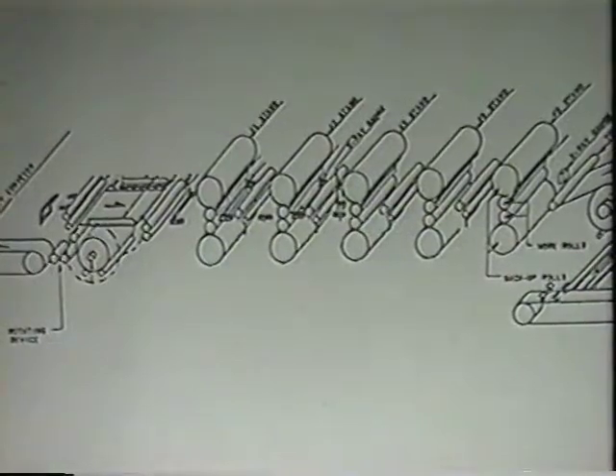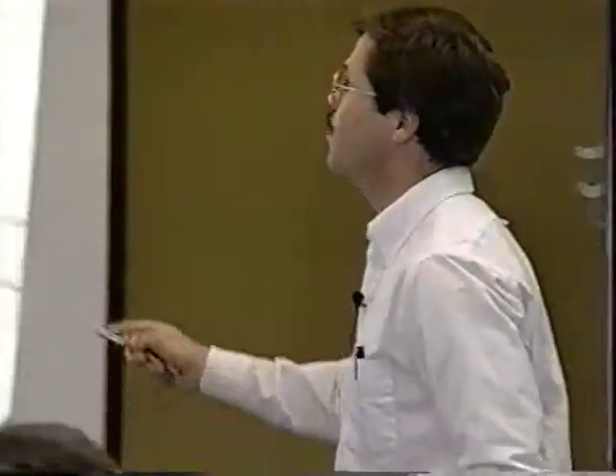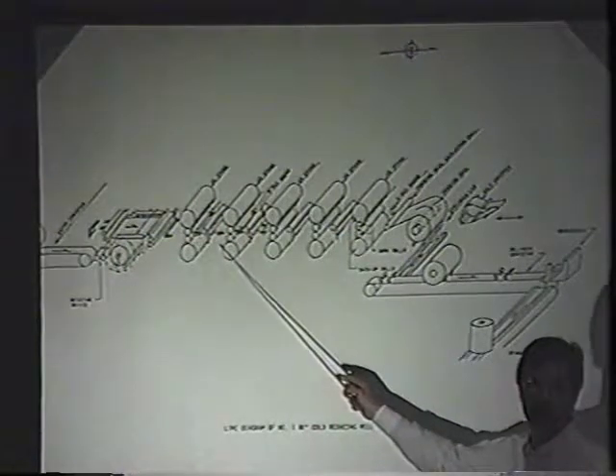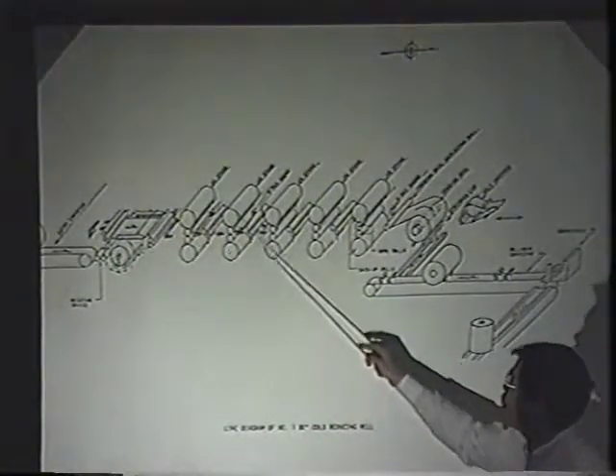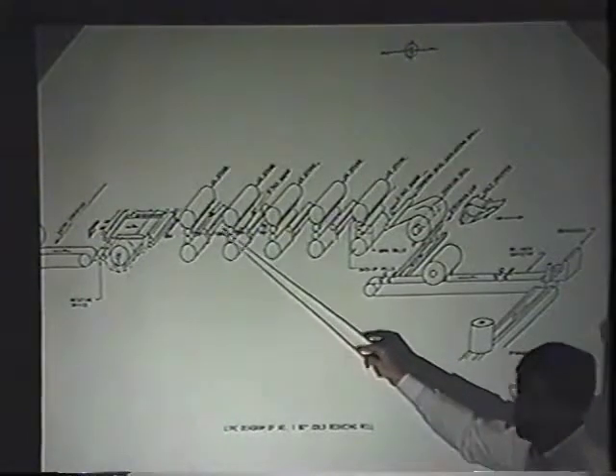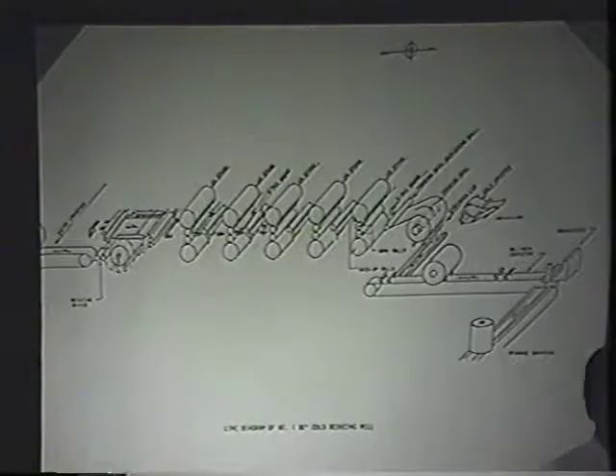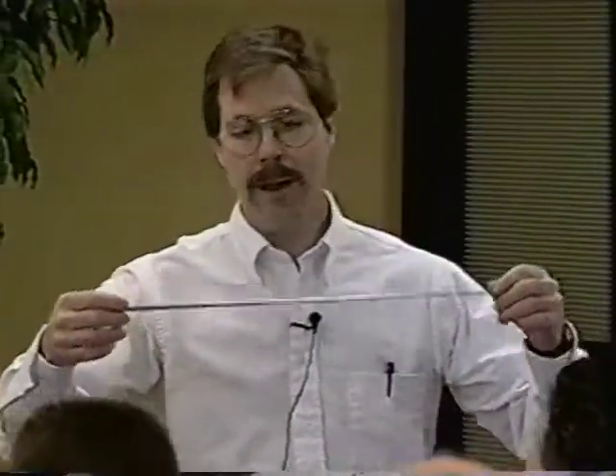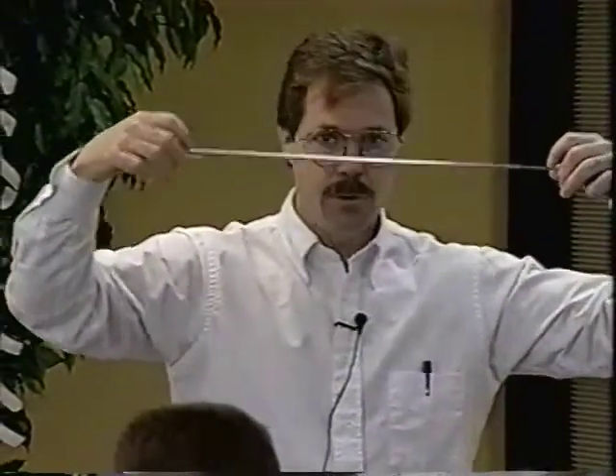2 work rolls, those are the rolls that are in contact with the strip, of small diameter, 25, 26, 27-inch diameter, backed up by what we call backup rolls of larger diameter. The purpose of the backup rolls is to provide structural rigidity for the work rolls. Imagine my pointer here is a work roll or a backup roll. It doesn't matter for this purpose. We apply the force at the ends of the roll. We don't apply it uniformly across the roll. The reduction force is provided at the end of it. The strip is in the middle of the roll.